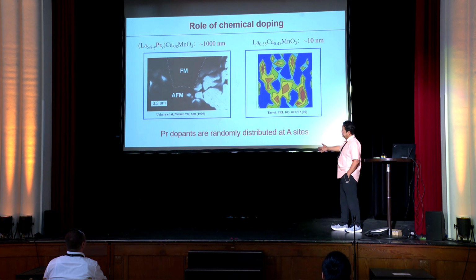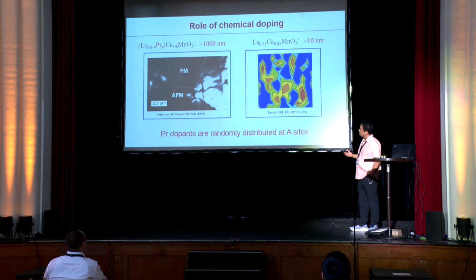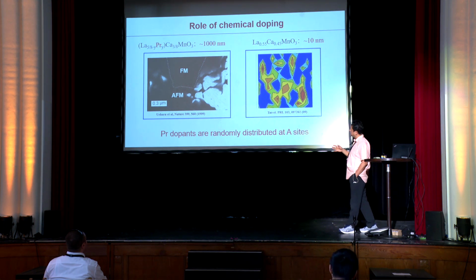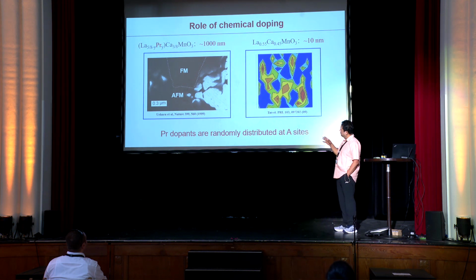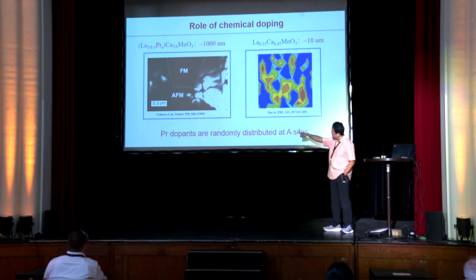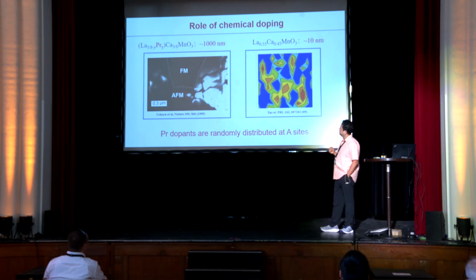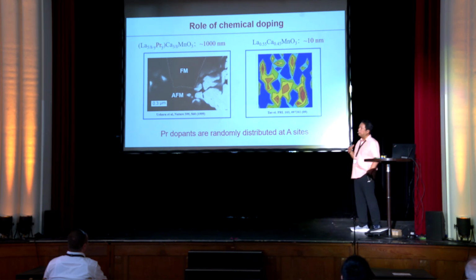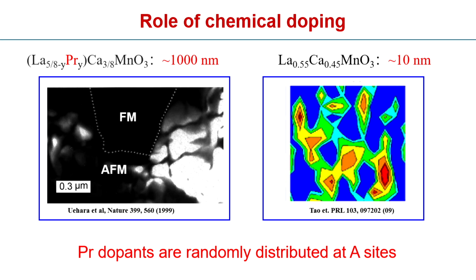I'm not going to get involved in discussing which theory is correct, but from an experimentalist point of view, we get into this problem. We look at some of these observations of electronic phase domains. The original report about electronic phase separation in this LPCMO system was made by Uehara in 1999, who reported that the domain size is on the order of micrometer scale. But the interesting thing is that if you take the praseodymium dopants away, then you notice that the domain size becomes a lot smaller, only 10 nanometer scale. So it looks like the praseodymium dopants are very important.